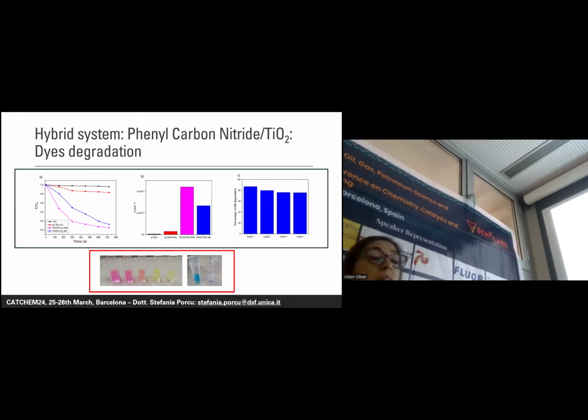After that, we had to study the recyclability of our catalyst, because you know that is a very important parameter for the material to be applied more than one time. And what we found was that for 4 cycles, we obtain almost the same rate of degradation, meaning that the photocatalyst can be recycled and reused multiple times, okay? Only washing and drying it, we can reuse the photocatalyst.